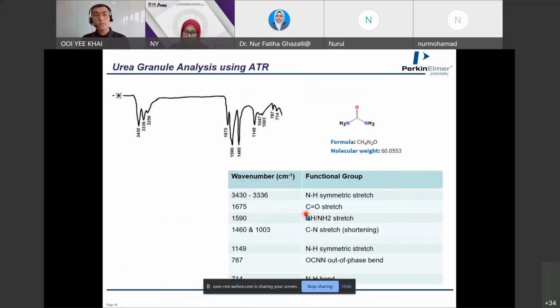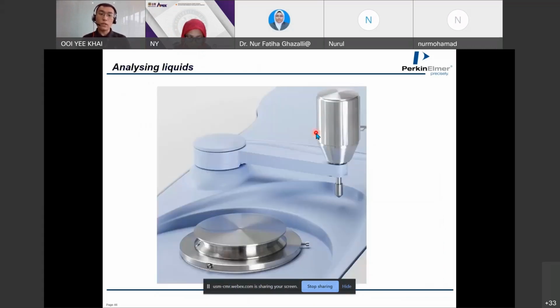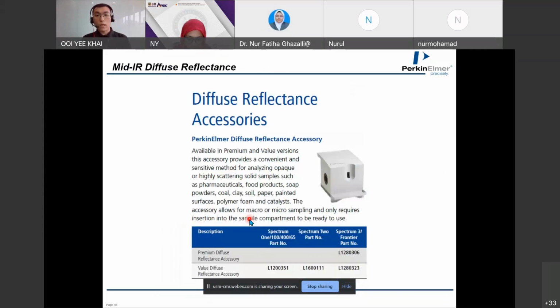For example, this is a urea granule, and this is the spectrum generated from the ATR accessory. We directly put it on top of the crystal, and then we just do a scan. If it's a liquid, you can just drop one drop on top here, then scan without needing to apply pressure, because most liquids have a certain wettability index, so they will spread out just nicely and cover the crystal.